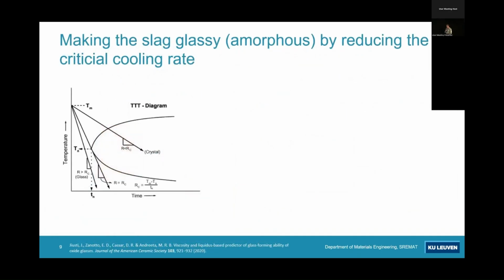So one more aspect to introduce. Liquidus temperature is important for us because that determines the processing temperature, but also glass forming ability. We want to create something amorphous. And if you want to create a glass or amorphous structure, we basically have to cool our material very fast. And for steel slags, it's very difficult. It's very basic, so it crystallizes very easily.